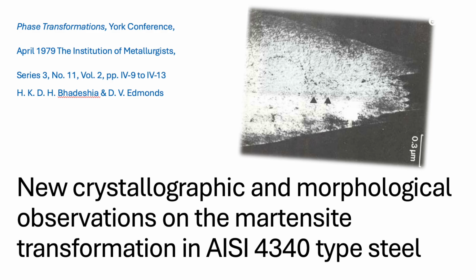If the packet is so good at managing strain, why does the steel sometimes form plate martensite? Good question. This brings us to the factors that control which morphology forms. And a major one is the initial austenite grain size. The size of the crystals before you quench the steel. That makes intuitive sense. Bigger spaces might allow for different structures. Precisely. The sources found a pretty clear relationship. When the initial austenite grains were relatively small, say around 100 micrometers or less. Which is still pretty small to us, but maybe not atomically.